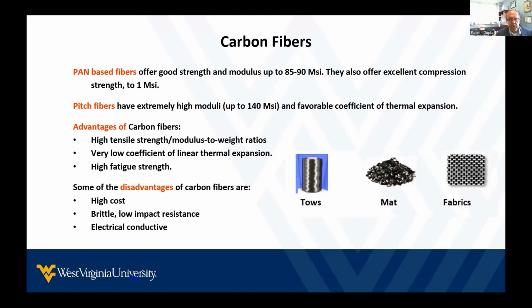The other major kind of fibers used are carbon fibers. Here one typically starts with a textile fiber and removes all but carbon atoms by heat treatment. And the textile fiber one uses is PAN, or polyacrylonitrile. It offers good strength and high modulus, also excellent compression strength. One can get even higher moduli if one uses pitch fibers, and the pitch could be typically derived from petroleum asphaltenes. And here one can go to a modulus of up to 140 MSI. The coefficient of thermal expansion of these materials can be relatively low, and this offers many advantages.